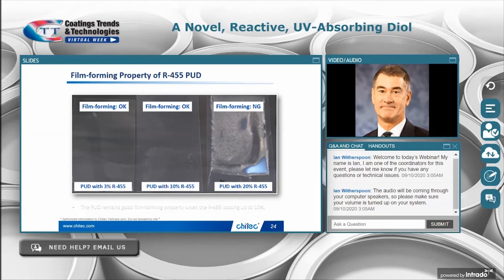And in this example, we're just showing the robustness of use for this diol UVA. We're trying to define the limits of loading. And you can see at a 20% loading, which is extremely high, we start to pervert the PUD, and it would need reformulation in the resin portion to get it to behave well, which we're not saying you can't do. I think actually you probably can do it. But in just a plug-in replacement type situation, we're fine at 3 and 10%. So really, it should be easy to incorporate the R455 into a variety of different polymer formulations, something that a good synthesis chemist can do quite easily, we think.